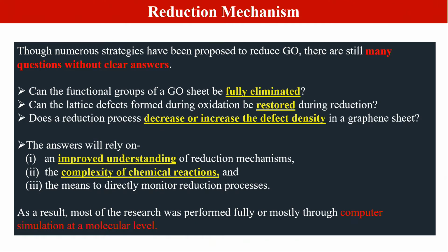The question is, can you fully eliminate the functional elements on the top surface and the side surface? Can we restore the graphene lattice structure, the honeycomb structure? If that is possible, our problem is solved. Then what is the level of defects, because that simply disrupts the lattice structure. If the lattice structure is disrupted, then the conjugated network is disrupted, then the electrical conductivity is disrupted. I told you 100% cannot be done, but if 20% exists, then we can decrease or increase the defect density and also the carrier density.